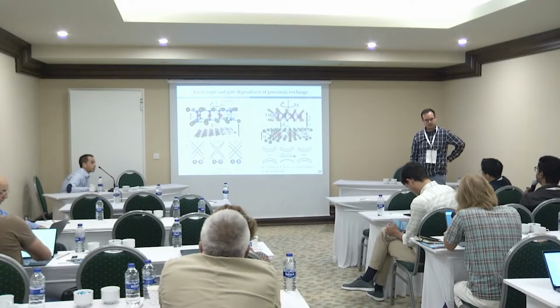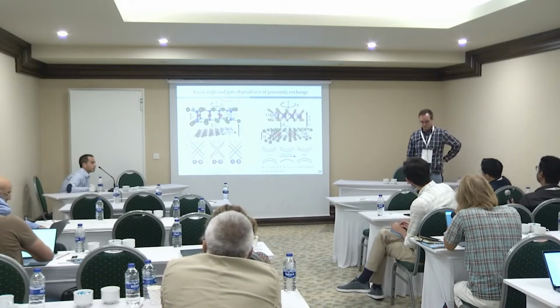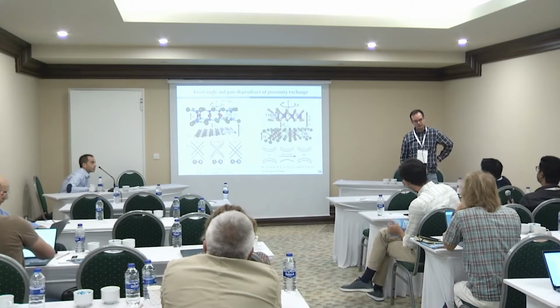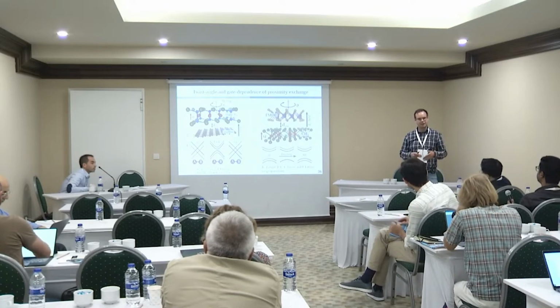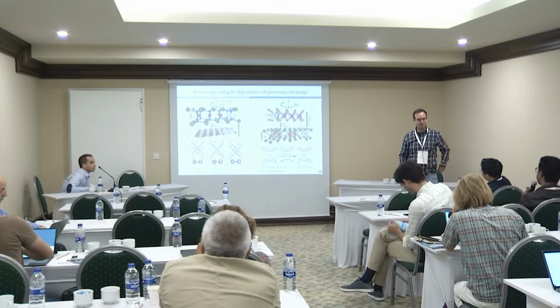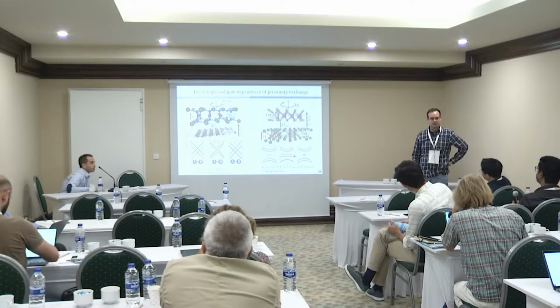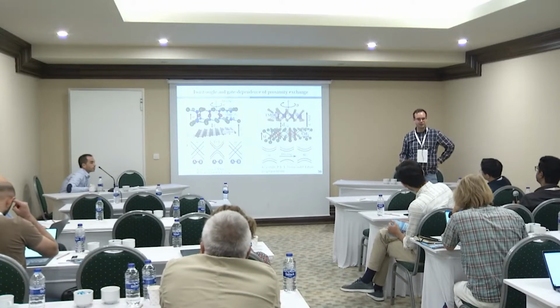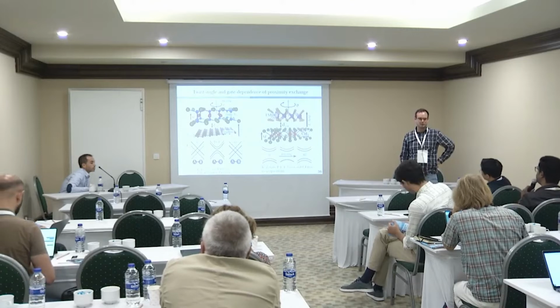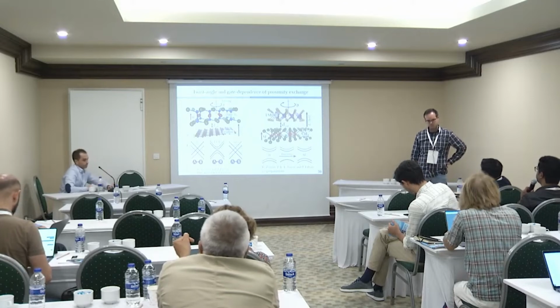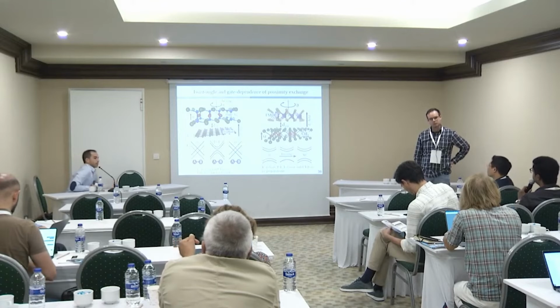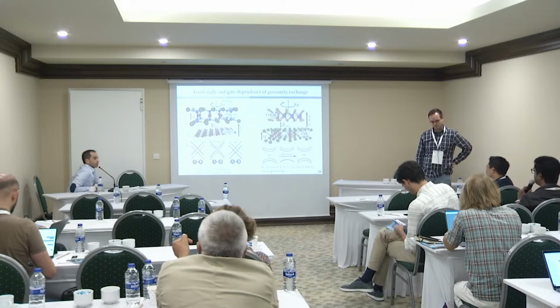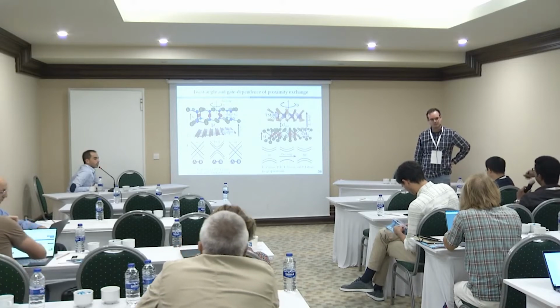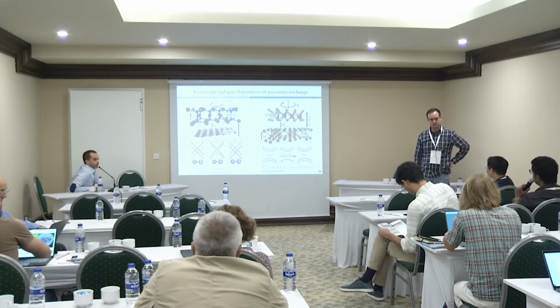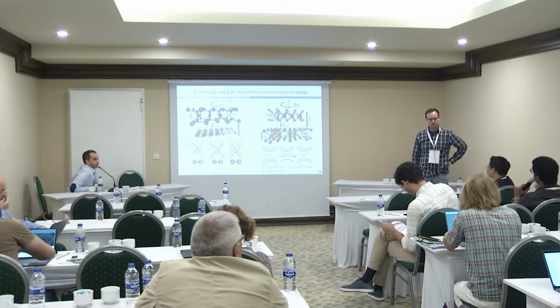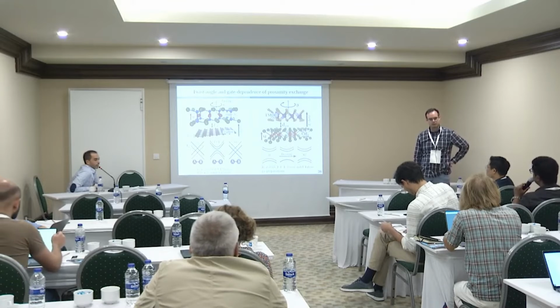With the perpendicular field, there is a small impact on the proximity spin orbit coupling, but you cannot switch it, because in this sense the bilayer structure is really completely different. Yeah, I know. So what will happen with the field? You mean what happens to the effective parameters once you apply the field? Exactly. Experimentally for bilayer graphene, people have found that if you have a phase diagram of D versus density, where D is the field and N is the density, the diagonal is the Dirac point. People have found some asymmetric dependence also. The asymmetry comes from the spin splitting. Yeah. So what will happen for the monolayer case?